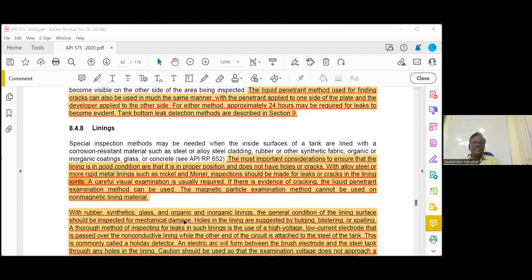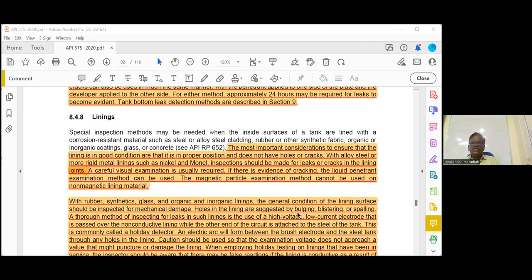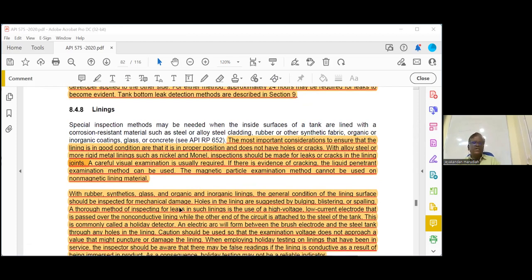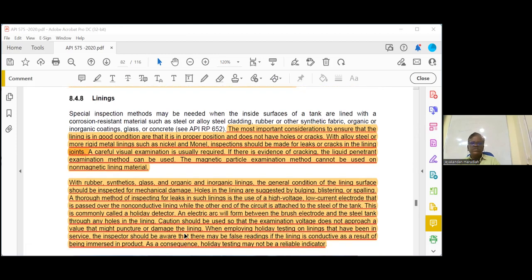With rubber, synthetic, glass, or organic and inorganic linings, the general condition of the lining surface should be inspected for mechanical damage. Holes in the linings are suggested by bulging, blistering, or spalling. A thorough method of inspecting such linings is the use of a high voltage, low current electrode that is passed over the non-conductive lining, while the other end of the circuit is attached to the tank. We call it a holiday spark test. This is commonly called a holiday detector. An electric arc will form between the brush electrode and the steel tank through any holes in the lining. Caution should be used so the examination voltage does not approach a value that might puncture or damage the lining.